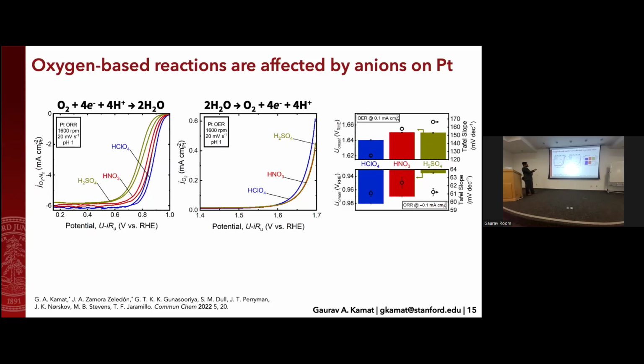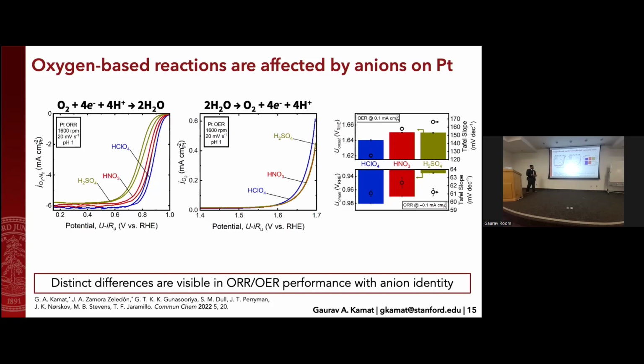So here you can see perchloric acid, nitric acid, and sulfuric acid for the ORR. You see that as you change from perchloric to nitric and sulfuric, you start getting worse and worse in catalysis. And on the right here, you have the exact opposite of oxygen reduction, which is oxygen evolution. And there you also see that perchloric acid is actually the best. The trend is flipped when you're looking at the opposite reaction. And then nitric and sulfuric are a little bit worse. And that's what these bars are essentially showing here. So we see distinct differences in both ORR and OER performance with anion identity.